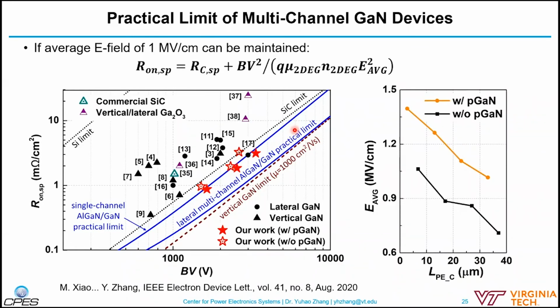So I can share some of our experimental observations. We actually tested the material and the devices, for example wafers with delta doping at each of the 2DEG channels, and also wafers without. With the delta-doped wafer, surely the sheet resistance can be even lower. But the problem is it's very difficult to manage the electric field and control the leakage current. It's very difficult to realize decent voltage blocking characteristics. And why is that? Some of it I think is still unknown.